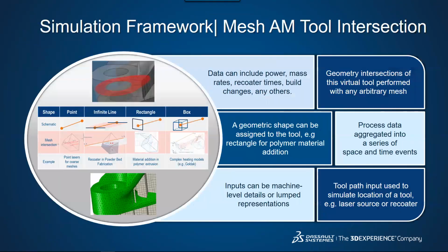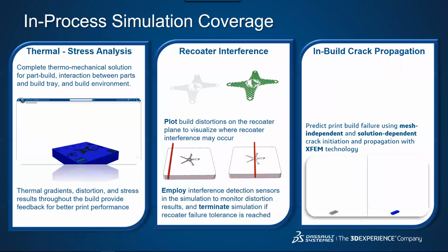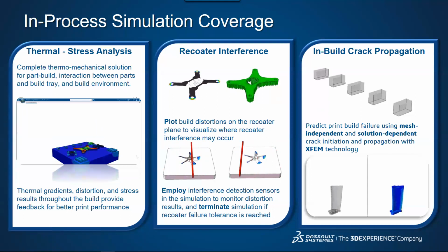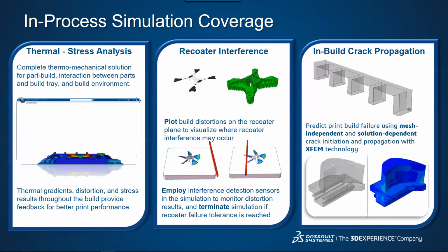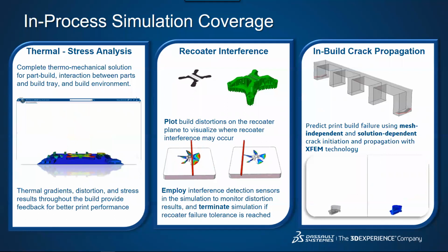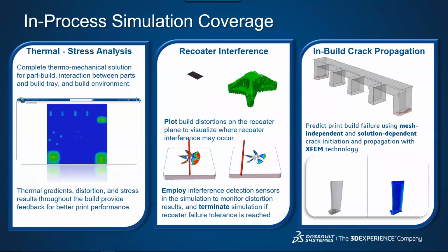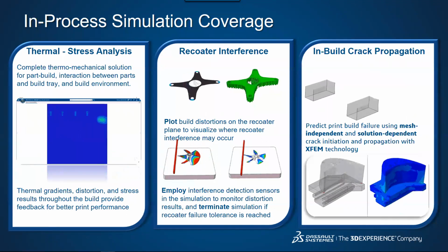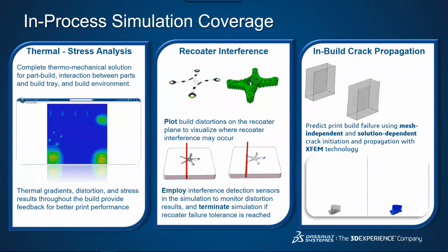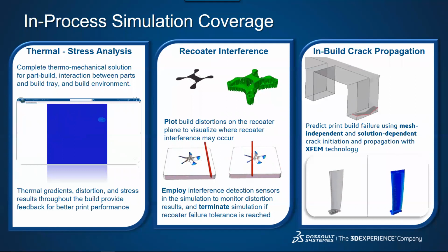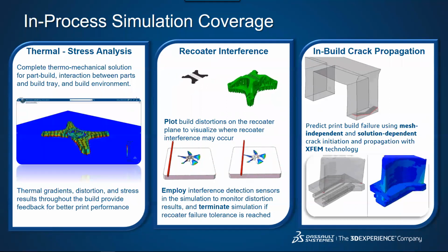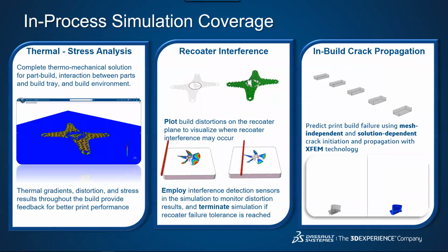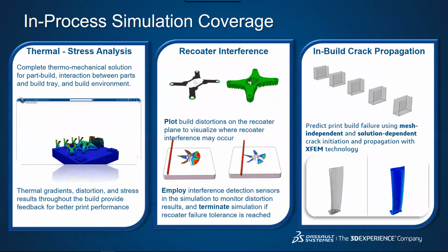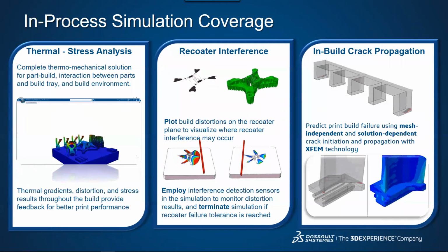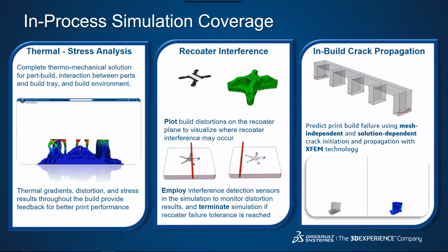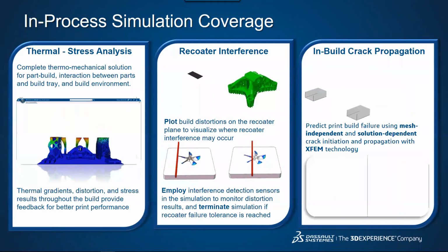Okay, so how do we do these process simulations? We perform the process simulations by doing sequential thermal stress analysis. In the heat transfer analysis, the real scan data, or the real laser path data, is used to calculate the heat flux. It calculates the heat flux by including the detailed temperature dependent material properties and the build environment. So we have the build tray and the ambient conditions also accounted for. And this is going to give us our resulting high accuracy thermal profiles for the build. We then use these thermal profiles to drive the stress analysis, and this is what is used to compute structural deformations and stresses. So that's the idea of how the overall simulation workflow looks.